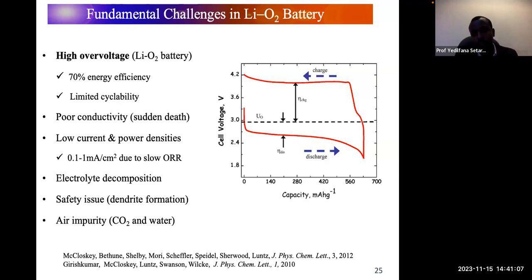When the battery works, we get around 2.6 volts. But when we charge the battery, we have to apply up to 4.2 volts, you see? So this is the disadvantage. We need to reduce the overvoltage in both discharge and charge. Particularly the charge overvoltage is a serious, serious problem in lithium oxygen. But this is a typical graph of the discharge and charge profile of lithium oxygen batteries.